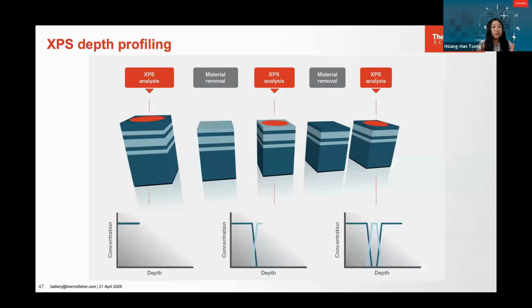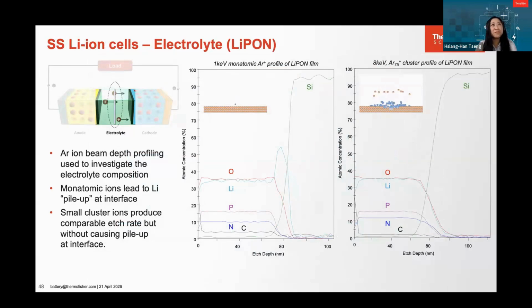Essentially, doing depth profiling is as follows. You take a spectrum of the surface of your sample, and then you remove some material, and then take the spectrum again on the new surface, and then altogether you create a composition profile from the surface into the bulk. So in the next slide, I can show you an example of this.